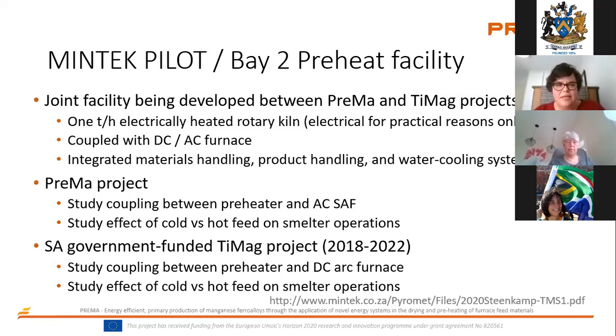So the purpose, as Eli said, of the PreMa project is to study the coupling between the preheater and the AC side. We know from industrial scale ferrochrome smelters in South Africa that have preheaters integrated in their flow sheet, as well as ilmenite smelters, that unstable operation of the preheaters destabilizes the submerged arc furnace, or the DC smelter in the case of ilmenite smelting, to such an extent that the plant operating personnel decide to rather switch off the preheater. They rather take the penalty of not drying or preheating the raw material and have a stable furnace operation than combining the two.